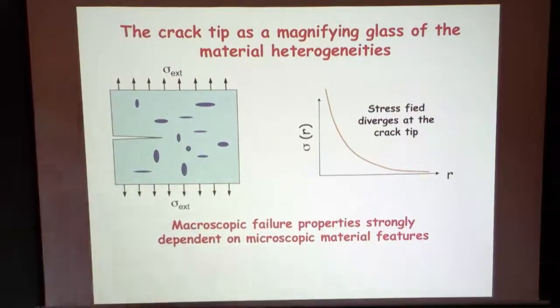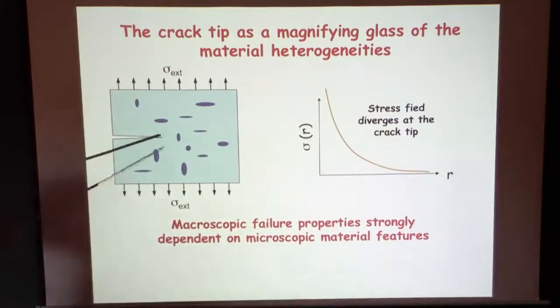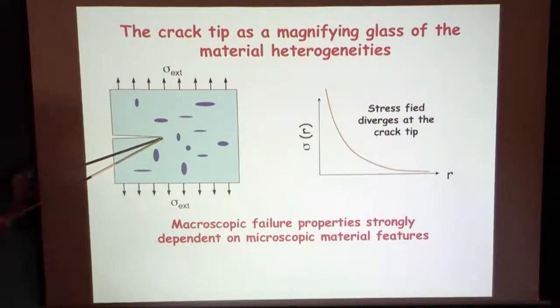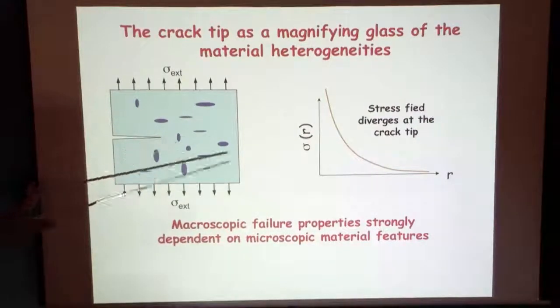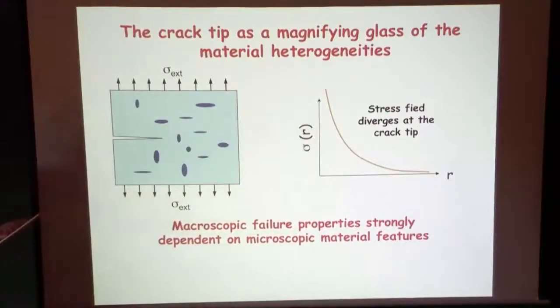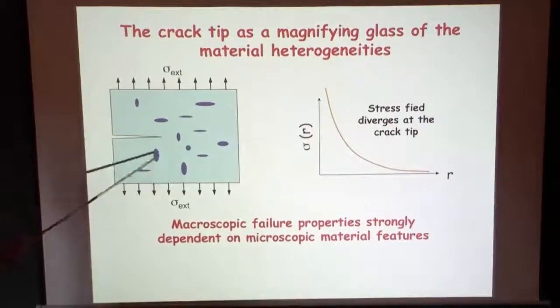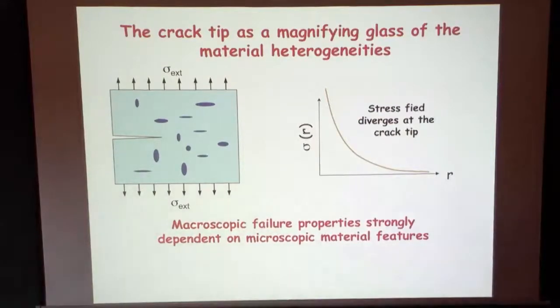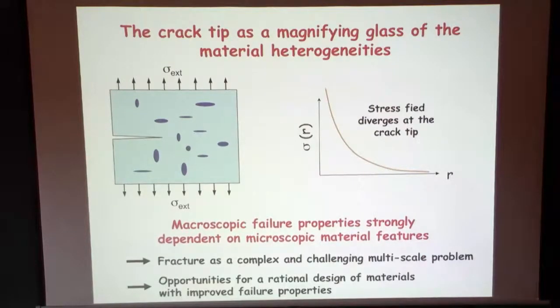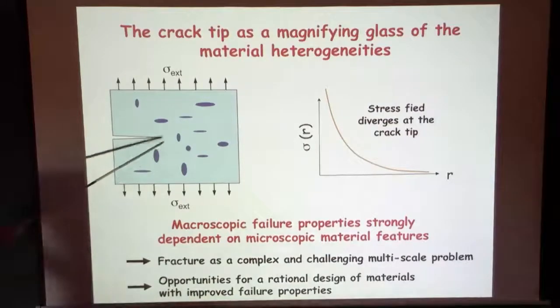We saw previously that the crack response is mainly governed by the prefactor K of the singularity, but it's also governed by the value of the resistance GC at the tip. So anyway, with this singularity, brittle fracture is a propagation of a singularity in your medium. You have an extra sensitivity to all the local properties, and you have a huge effect of local property on overall behavior. That's the reason why fracture is going to be a complex multi-scale problem. It's not going to be very simple to go from small scale to large scale.